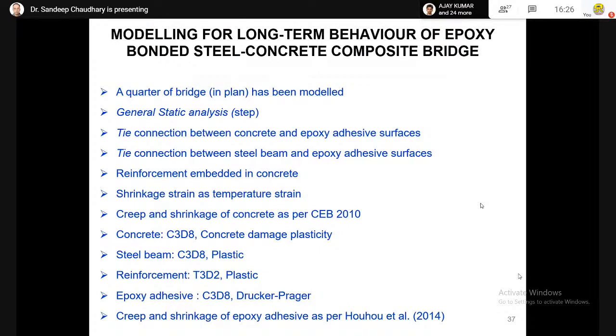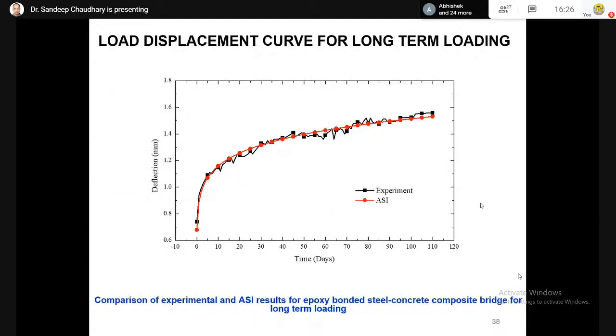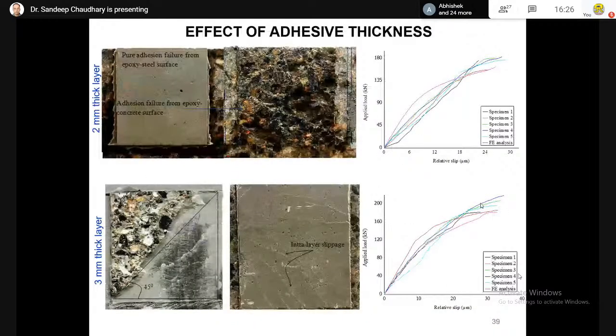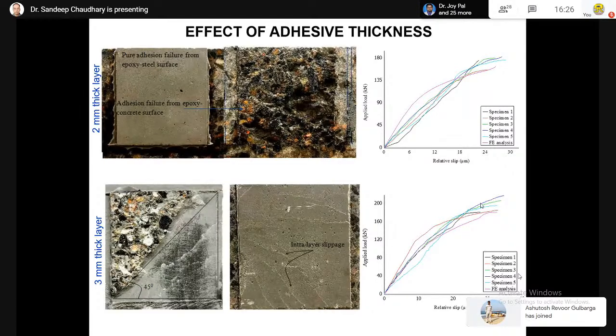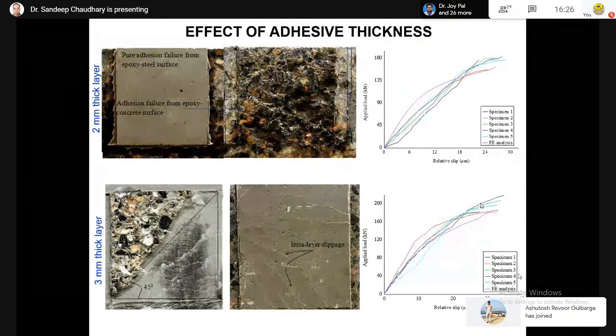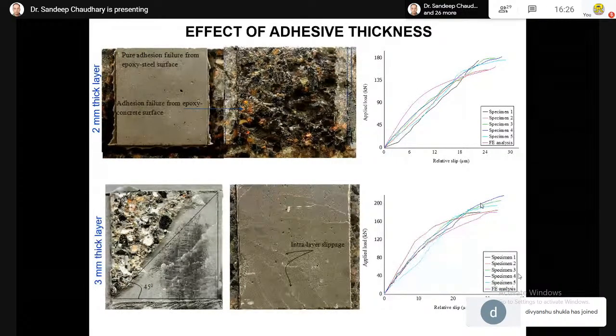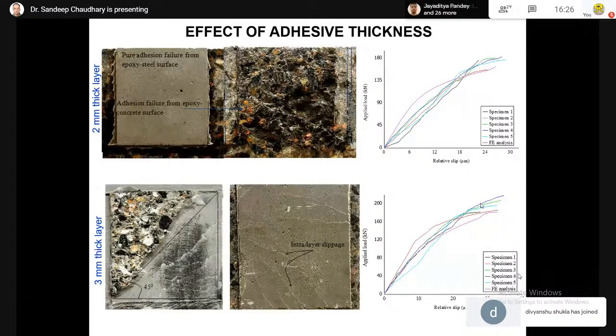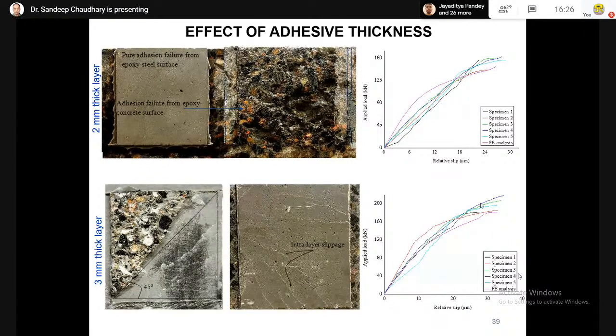And of course, a quarter of the bridge was modeled and general static analysis, tie connection was ensured. So these are standard terminologies of the finite element method. They were adopted. And so here you can see the results. We also tried to see the effect of adhesive thickness, that is, does it affect the behavior of composite action. So we got some interesting results that when we used a 2 mm thick layer, and we used a push out test, we saw a pure adhesion failure at the epoxy steel surface. So there's a pure adhesion failure here.